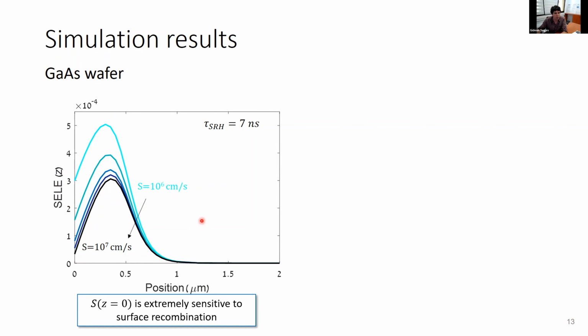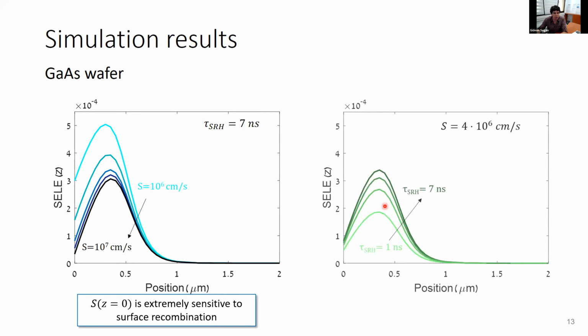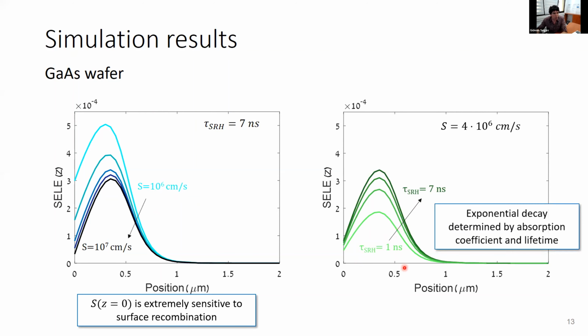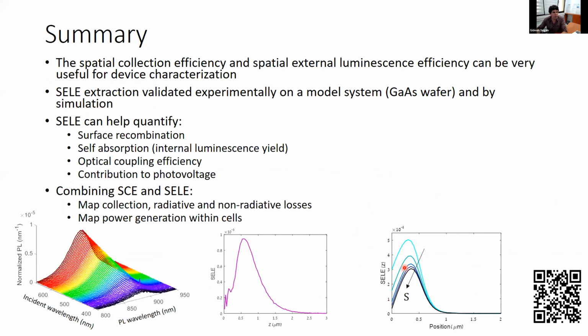We can do the same by looking at different bulk lifetimes, and as one would expect, by increasing the bulk lifetime, you can increase the depth from which photons can be extracted from the device. So all in all, we have seen that we believe that spatial collection efficiency and spatial external luminescence efficiency can be very useful tools for device characterization.